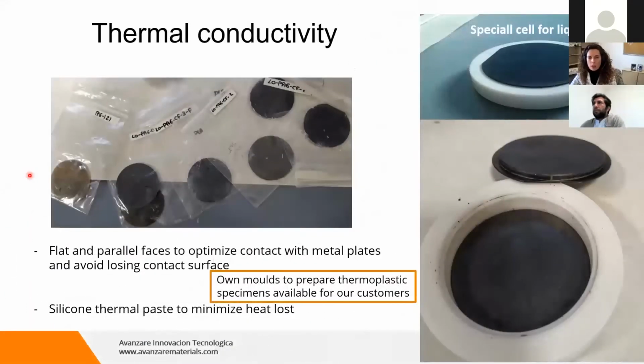So the kind of specimens that are required to determine the thermal conductivity by this method, which is based on the standard ASTM E1530, is a specimen with flat and parallel faces of 5 centimeters of diameter, and we can provide our customers, in case of need, with the molds to inject the samples. Okay. In case we are working with fluids, we have this special cell with the same dimensions. We fill it with the sample here and we put it inside.